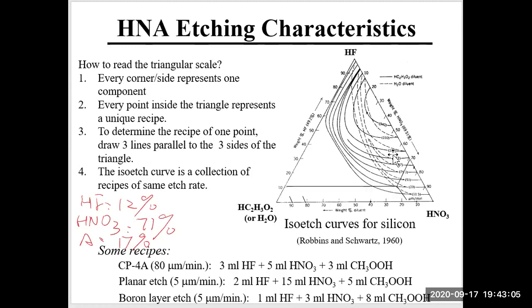And then we can find many other isoetch curves. The solid curves represent the isoetch curves for acetic acid, but dashed lines are isoetch curves for water, when we use water as a diluent. So that's the difference between solid curves and dashed curves.